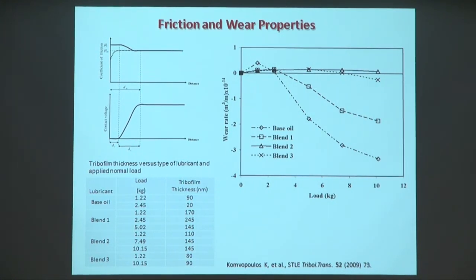And what you can see here is that if we plot the wear rate as a function of load applied to these wearing surfaces, you can see that initially we have no wear or positive wear. Positive wear will indicate that the tribofilm is forming faster than it is removed. So something is deposited on the surface. So instead of having loss of material, you have extra material. And there is a transition to negative wear, that is loss of material, that is affected by these different blends.